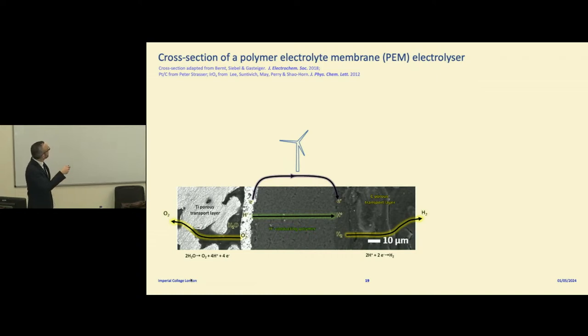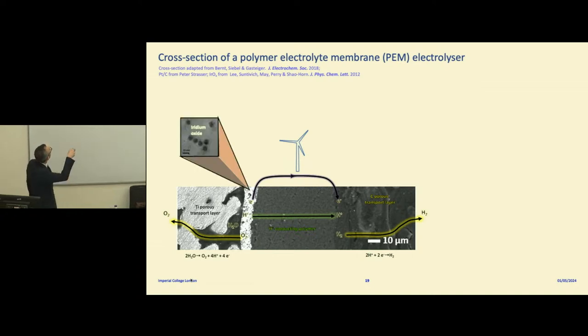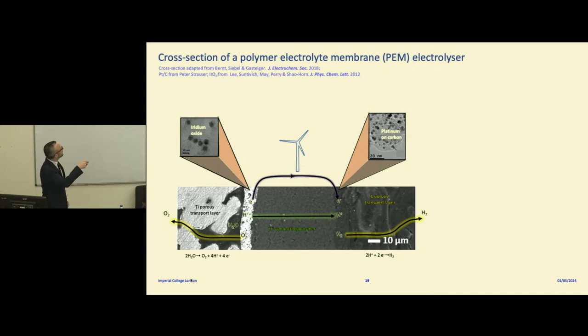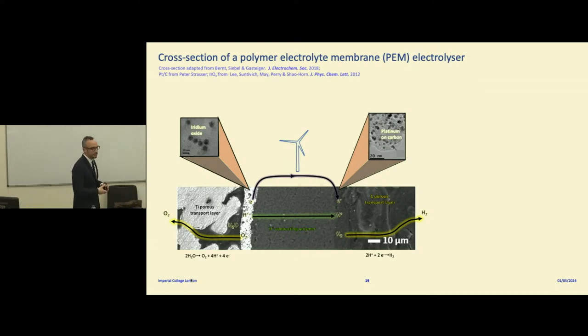You have in the middle a membrane that only conducts protons, and at the sides you have the electrochemical reactions. You have hydrogen being evolved on one side and oxygen being evolved at the other side. The electrocatalyst is actually these little nanoparticles here. You have iridium oxide nanoparticles at the anode electrode, and then you have platinum dispersed on carbon at the cathode. The ideal way of testing different electrocatalysts would be to take the actual device and put it together.